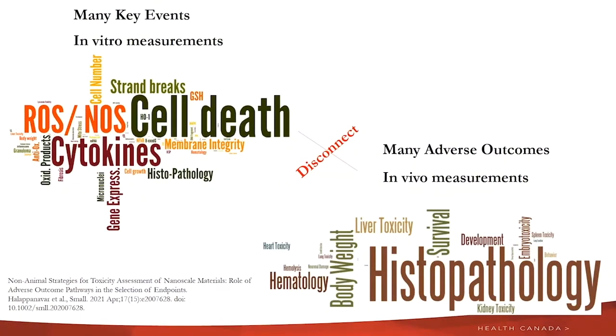Basically, in this slide, what I'm showing you is the different types of key events that are measured in vitro versus in vivo. The larger the size of a word, the larger the number of studies that have measured that particular endpoint. What we observed is that what we measure in vitro and what we measure in vivo have no connection. There is a large disconnect between these measurements, and that was one of the basic outcomes of this exercise we did as part of the OECD WPMN project.